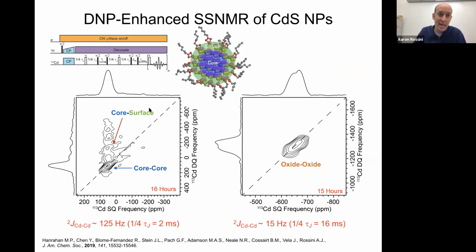We can also do cadmium-113 INADEQUATE single quantum, double quantum correlation experiments. These are nice because we are using the 2-bond cadmium J couplings. So cadmiums that share a sulfur will be J coupled to one another. Those J couplings are about 125 hertz, based upon the mixing time that we use in the INADEQUATE experiment. And doing those types of experiments, we can also directly see the link between those surface and core cadmiums.